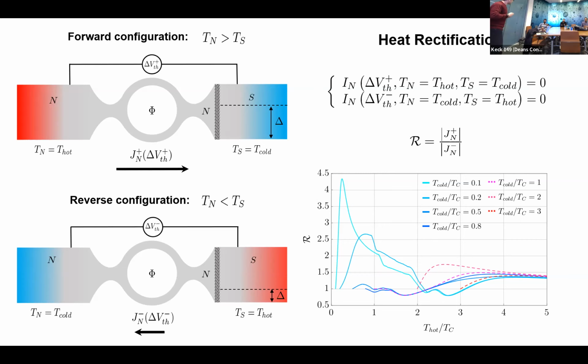If you suppose an open quantum system, then you don't need to put the charge current to be 0 every time, right? No, you have to. I mean, you are in an open circuit. This is something that Giazzotto stressed a lot. He has a couple of papers with Bergeret and these guys. I mean, you're in an open circuit configuration, meaning that the current through your device should be 0 when you apply the thermal current. And it's very important to compute your heat currents at the thermal voltage that makes the electrical current through the system equal to 0.